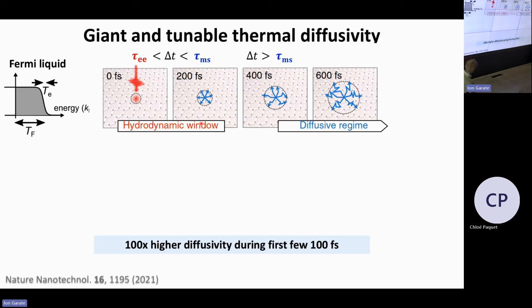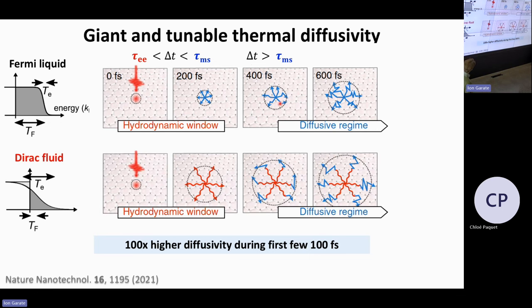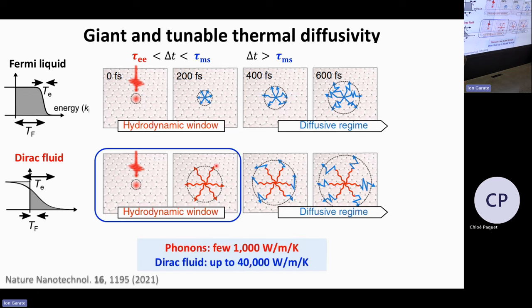So in the Fermi liquid regime, you have maybe some ballistic broadening, but nothing special. And then after a few hundred femtoseconds, you get diffusive broadening with this diffusivity that's on the order of 1,000 centimeters squared per second. Now, if instead we're in this Dirac fluid regime, so close to the Dirac point with a high electron temperature, you have this short-lived but very fast broadening of electronic heat, which we show here with these wiggly lines that are spreading out a lot in just a few hundred femtoseconds. And after that, of course, you get the same diffusive broadening.